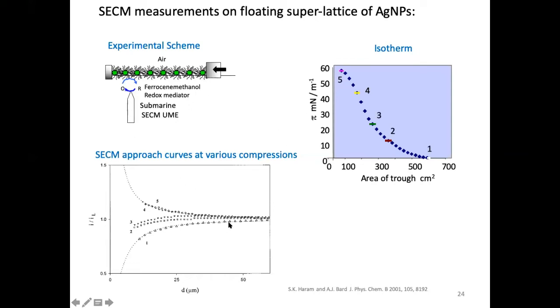Okay, obviously I expect negative feedback. That's what I see over here in the plot 1 approach curve. But once I start applying more and more pressure, the film is getting into conducting mode, and you can see eventually it becomes completely conductor and gives positive feedback. So it's clear-cut evidence that this transition does occur in this kind of film.